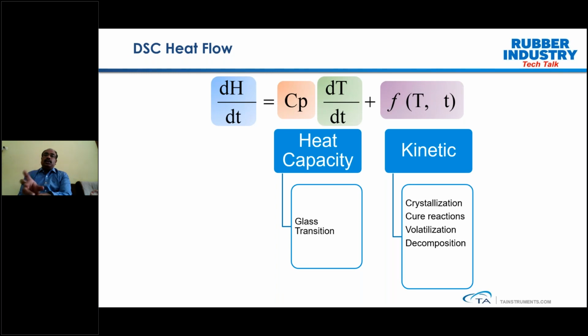The fundamental equation has two terms. The heat flow changes happen due to two aspects: heat capacity changes and kinetics. Heat capacity change happens, for example, as the sample undergoes the glass transition temperature. Your heat capacity changes before and after the glass transition temperature, so the DSC can detect that as a heat flow change. When a sample undergoes changes with respect to kinetics, for example a rubber compound which undergoes a curing process, that can be measured as a function of temperature. That also alters the heat flow. So this gives the complete information on how the sample changes its transition or the associated kinetic transition, and we are able to quantify the heat associated with that particular transition. So that's about the Discovery DSC 2500.